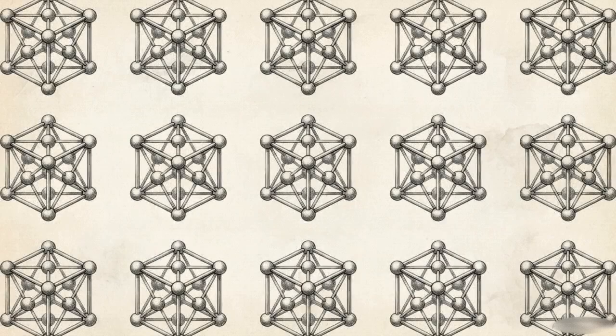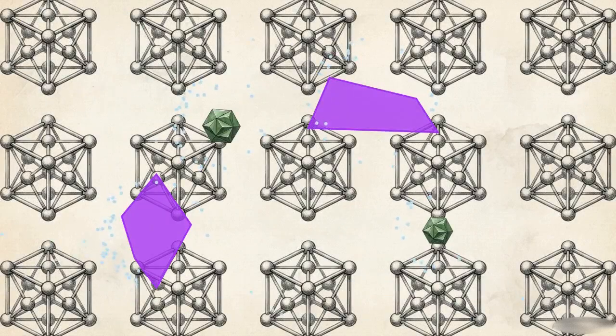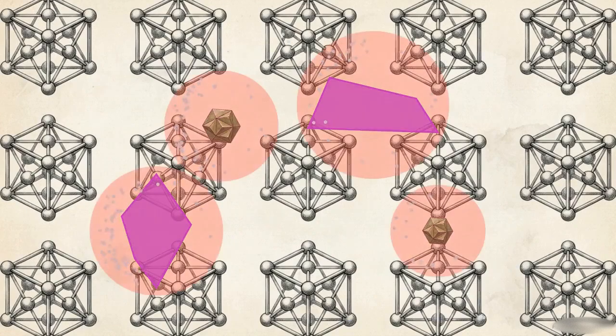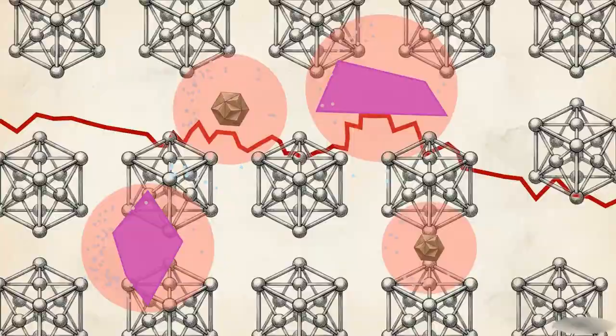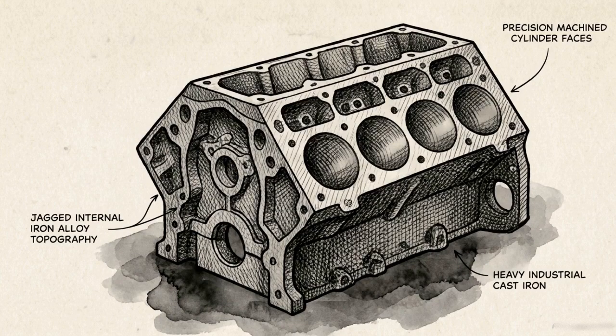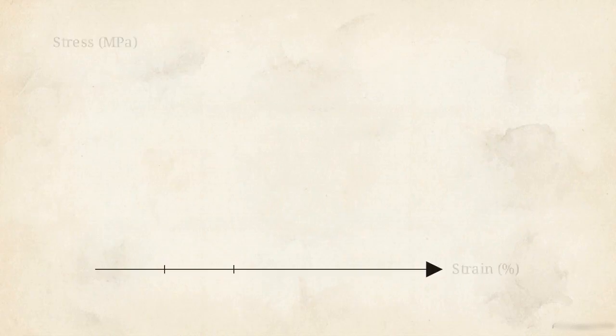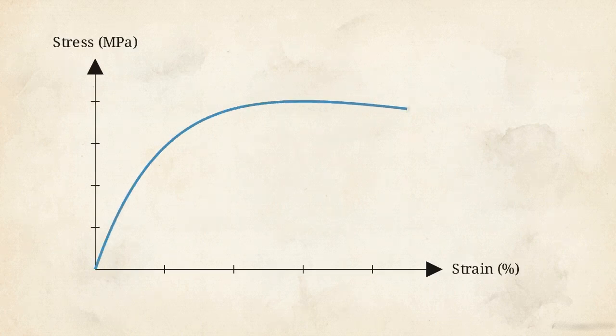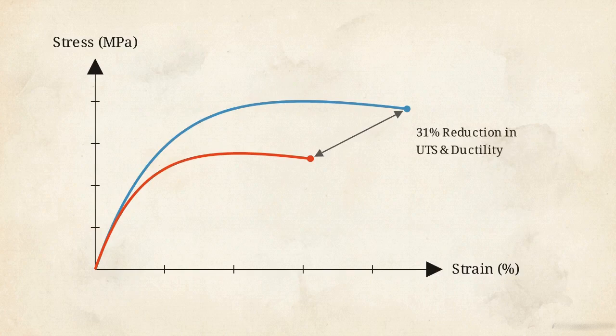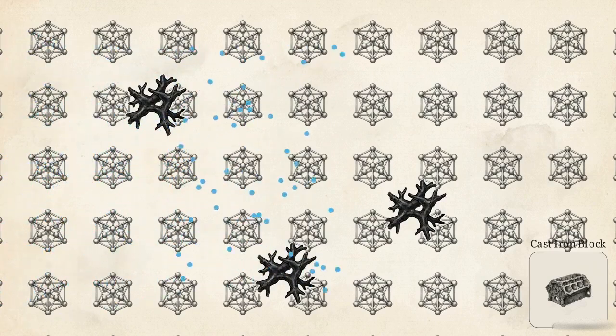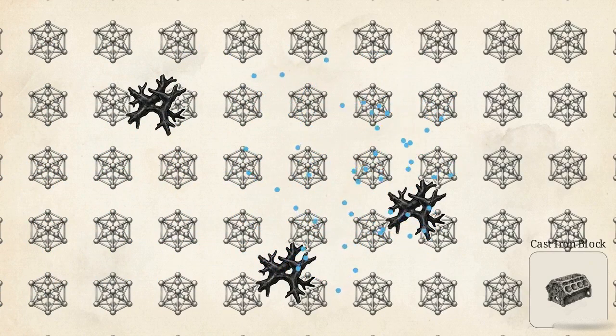The microstructural reason for this failure was clear. Silicon particles and intermetallic phases within the alloy acted as high-density hydrogen traps, matching the theoretical model. Next, they tested the gray cast iron used for the main engine block. This graph reveals the results for the cast iron. The hydrogen-charged specimen exhibited increased brittleness, resulting in a 31% reduction in ductility and ultimate tensile strength. In this case, hydrogen interacted specifically with the graphite flake morphology of the gray cast iron, creating a different failure threshold than the aluminum components.